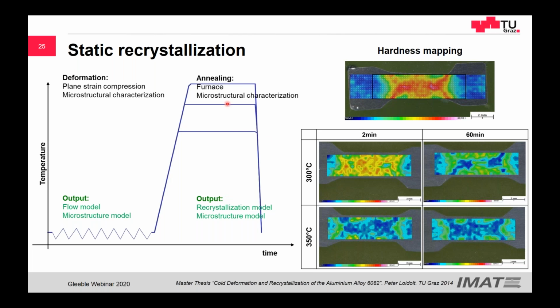So therefore, we have done this in the furnace. We also did it in the Gleeble, but after what we saw, we compared and did it in the furnace. And what you can see is now the softening. So here red are the strain hardening parts, and you can see that the first part that recrystallized, that softened, of course, is the part that had a very large stored energy, very large strain. And here you can see how some parts still remain with the same hardness, probably because we didn't reach the critical strain for recrystallization.